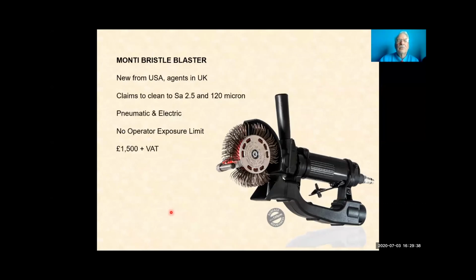Here is a rotary bristle brush, which has been invented recently. It's being marketed quite widely in the UK now. The problem with any rotary wire brush is that it tends to polish the surface. So what they've done here is put a little bar in the way so that it flicks down onto the surface to try and peck at it like the needle gun, but it still does polish it. There are two big problems with this. If one of these gets loose, they can do a lot of damage if they hit somebody, if one of these little wires gets away. The other thing is, look at the cost. I don't know what that is in rupees, but these things are very expensive. So I'm afraid we don't use them.